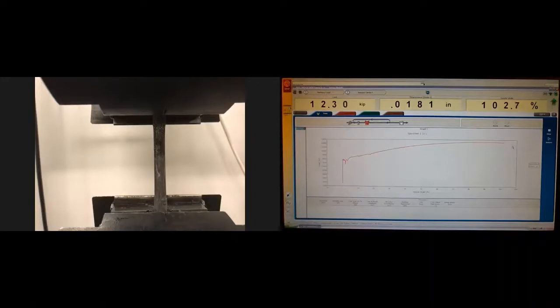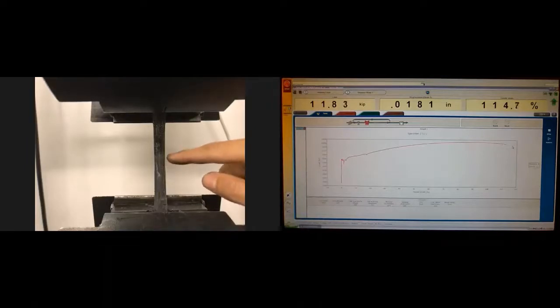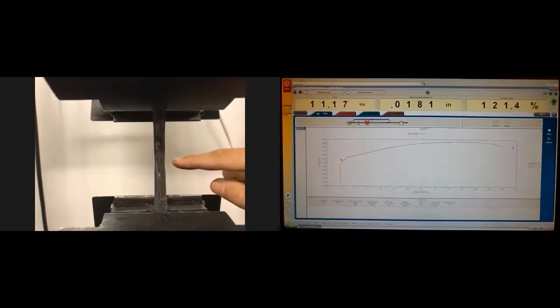And what it also means is that the movement of dislocations is not harmless anymore. So the material started to accumulate some damage, some voids and microcracks started to generate, and these dislocations are part of this process. So after piling up, they exhausted all the strain hardening capacity of the sample, and now they act actually against the sample's integrity. So probably somewhere around here you start seeing the change in shape, and this is where I see the necking. A dramatic decrease in diameter of the sample started to occur somewhere here, where my finger is.